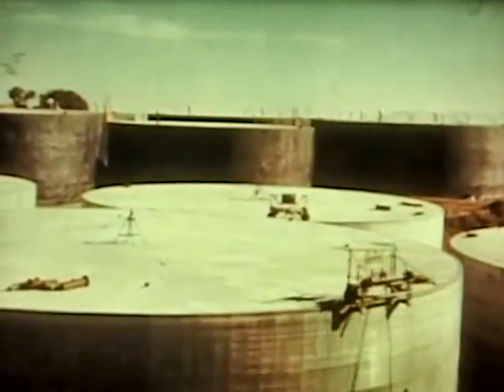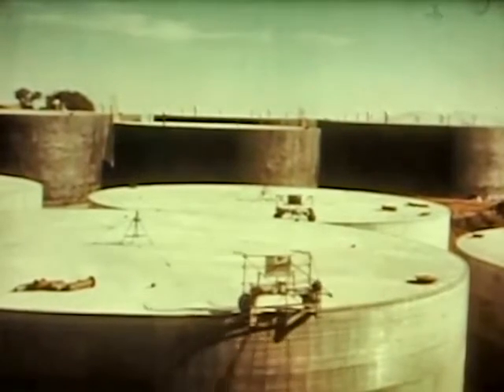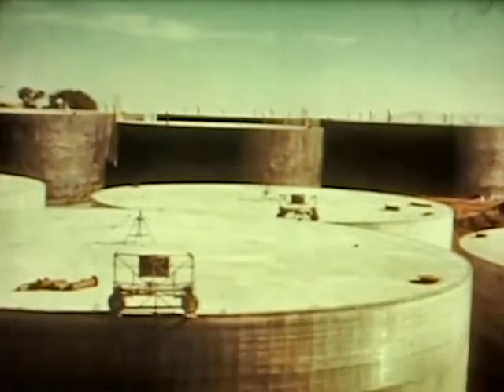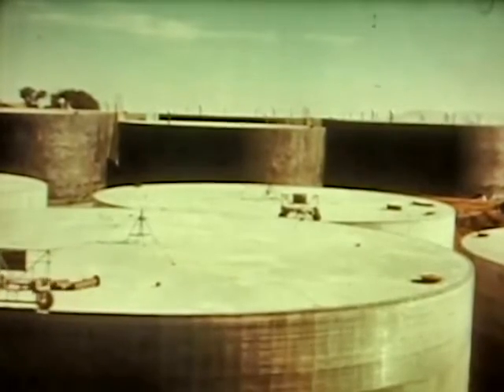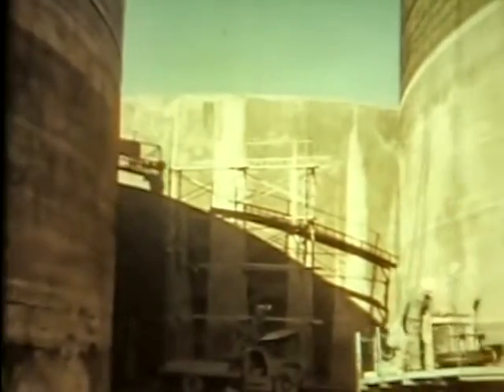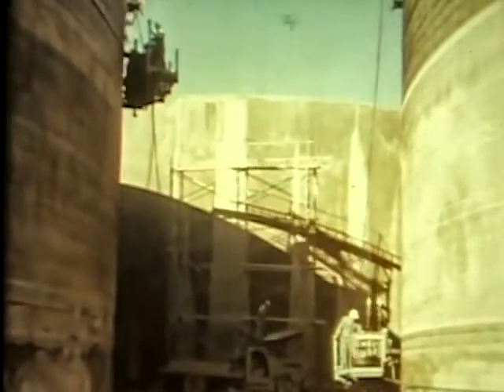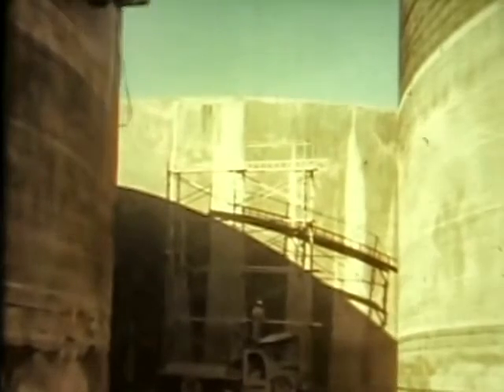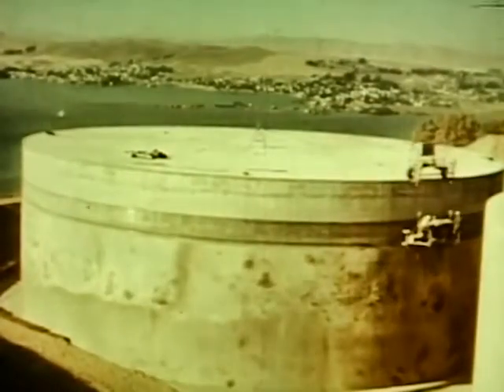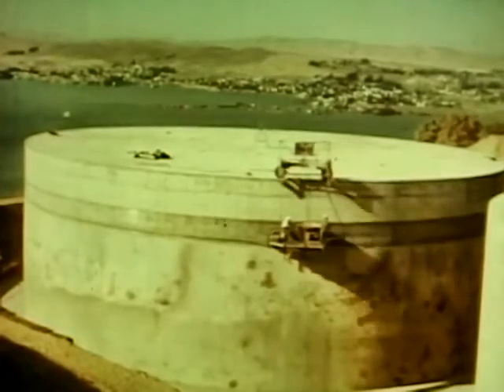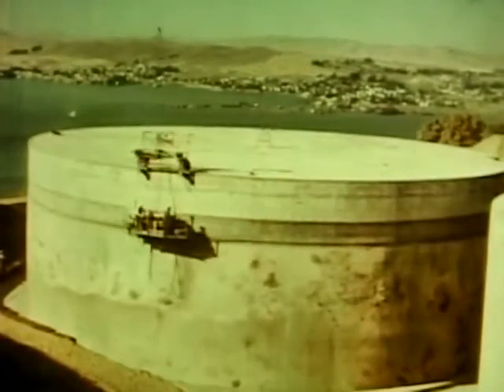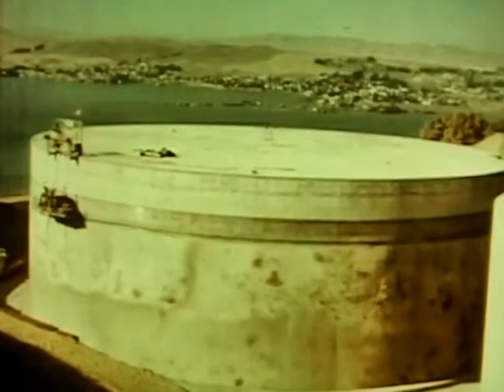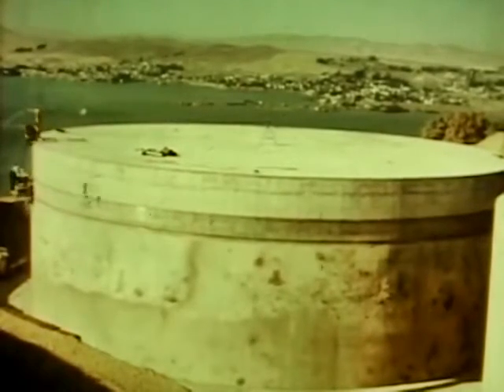The wire winding deck is suspended from an overhead carriage encircling the edge of the roof. The carriage is anchored by cables to a center pin. The wire is applied in 4 layers at the bottom, tapering off to a single layer at the top to conform to the design loads. The machine can install 10,000 pounds of wire in an 8-hour day. Each tank requires 56,000 pounds.